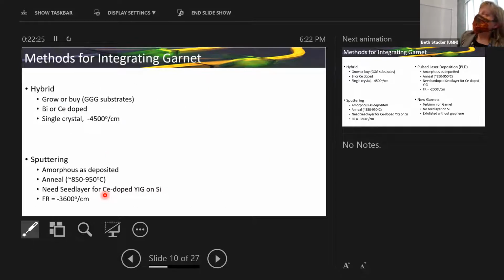So hybrid approaches: you grow your own or buy garnet, like a doped YIG, which are the best Faraday rotators on GGG—that's gadolinium gallium garnet, which is just a good substrate. You can get rid of that substrate or just thin it if you don't like it, or if it doesn't matter, because you're going to take your silicon photonic chip and paste the garnet down on top of it. That's one way to make sure there's garnet next to your silicon waveguide. You do want this doping for high Faraday rotation—single crystals get like minus 4,000 to minus 4,500 degrees per centimeter.